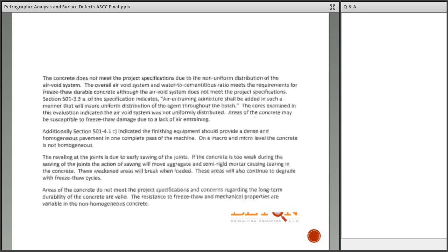No longer do we spend a lot of time talking about the joints. Now we're going to talk about the air voids. And I want you to read that upper sentence. The concrete does not meet the project specifications due to the non-uniform distribution of the air void system. There's no such requirement in the specification. You continue reading, you'll find out that you're supposed to uniformly mix in the admixtures, which is not really news, but there's a leap made, and that leap is that non-uniformly distributed air voids are a consequence of non-uniformly distributed air entraining agents, and that's simply not the case.